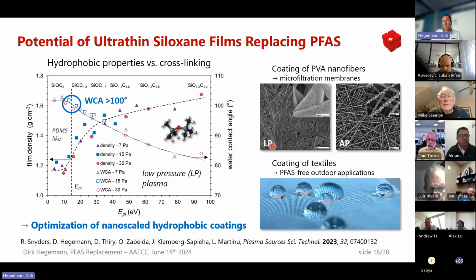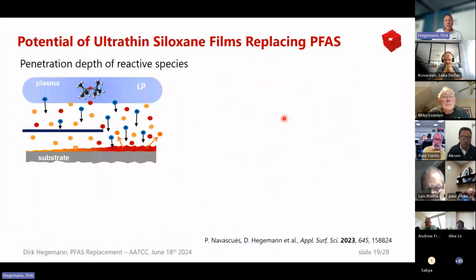This can be applied on scaffolds, on textiles, and here you see its advantages to do this at low pressure, LP, compared to atmospheric pressure, because in low pressure you have a better penetration of those plasma activated species into a complex 3D shaped structure. That can be further shown if you look at the surface that is directly exposed to the plasma or shielded from the plasma, so that you have only diffusion contributing to your film growth.